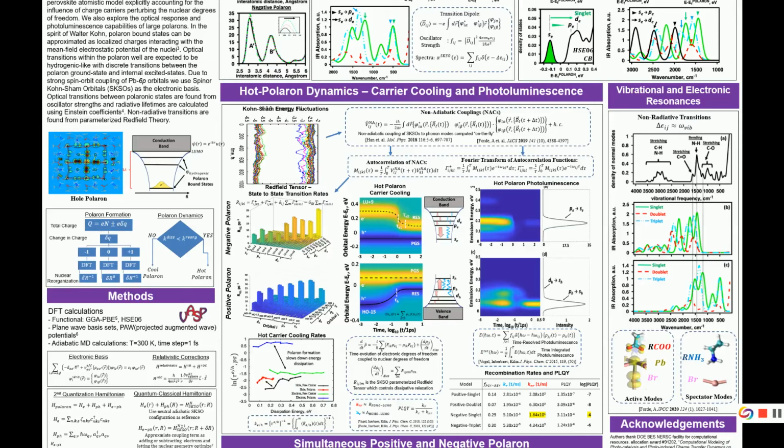So yeah, that's how we explain the trend that we observe from our recombination rates. And so that wraps up the story of having individual polarons in the models. The main takeaway is we do see consistent signatures of polaron formation due to either bond elongations or coordinations occurring between halides. And these polarons do have spectral features from transition to the excited states.